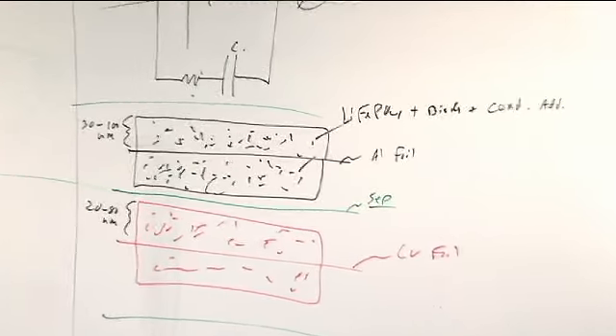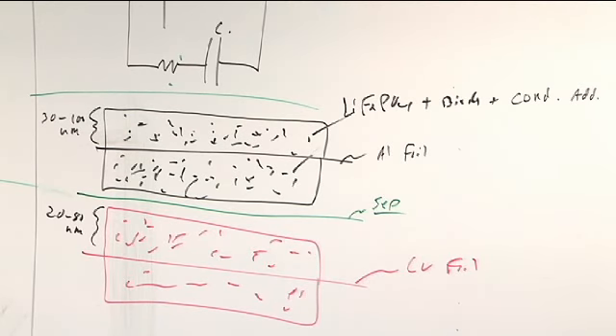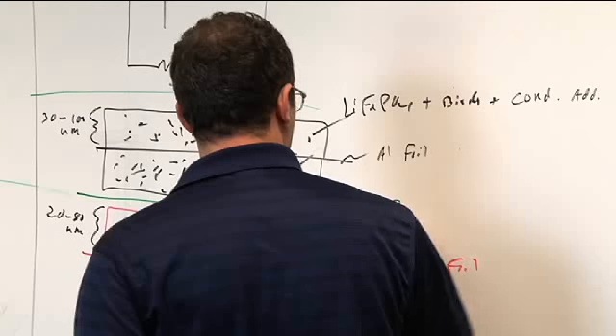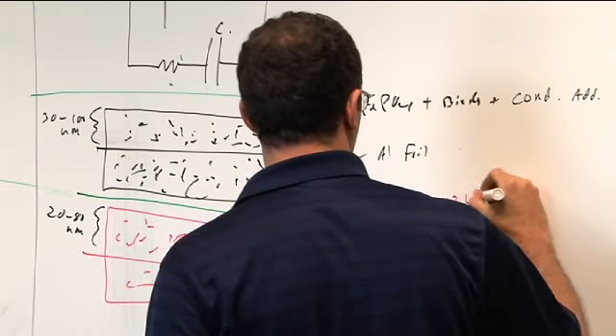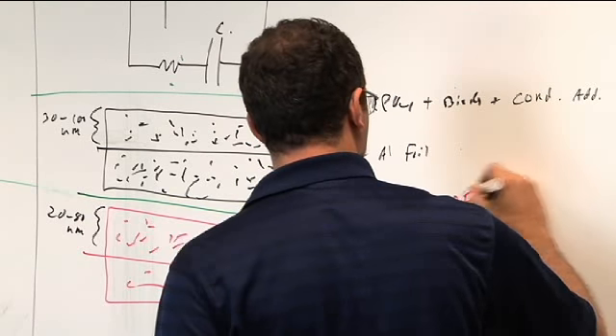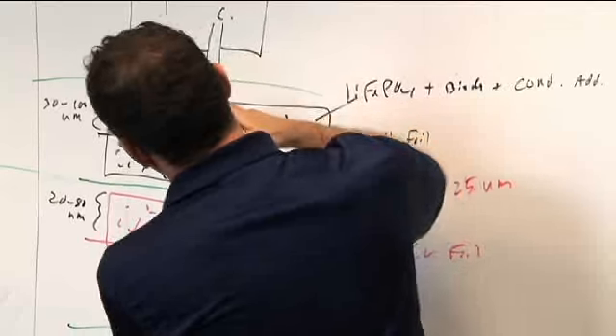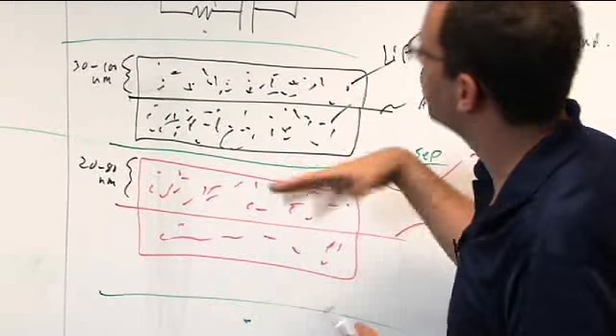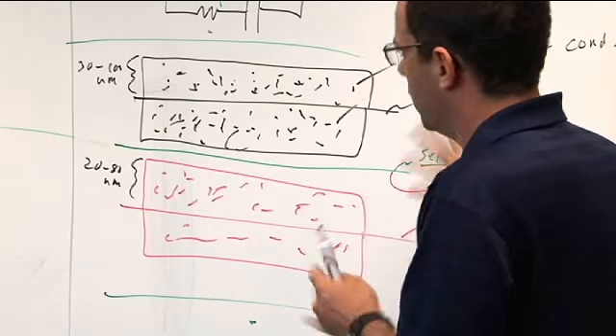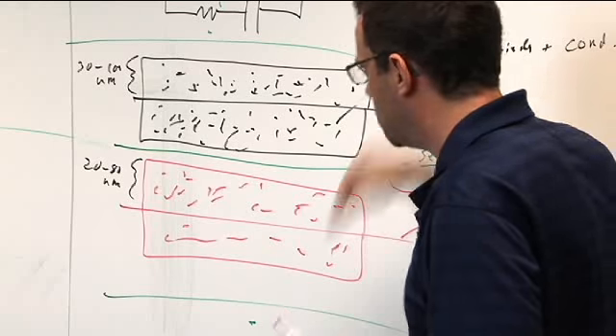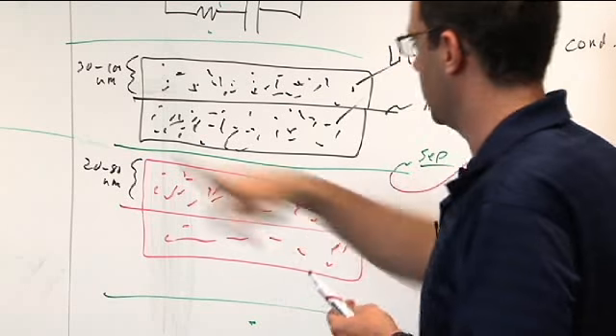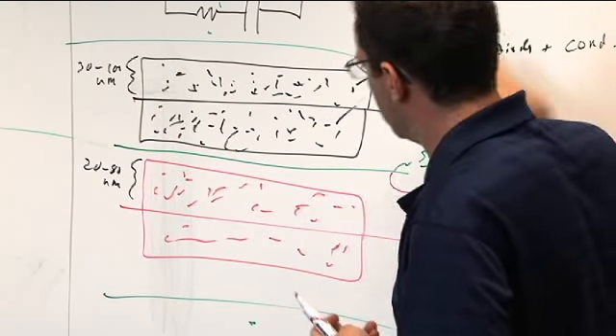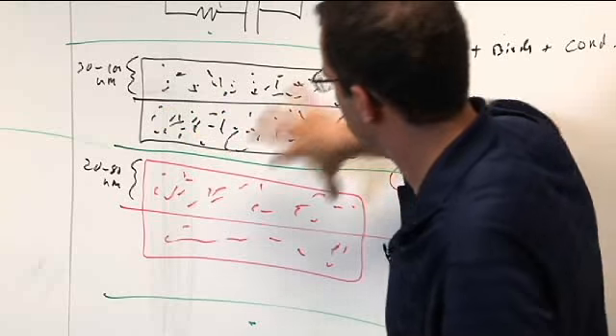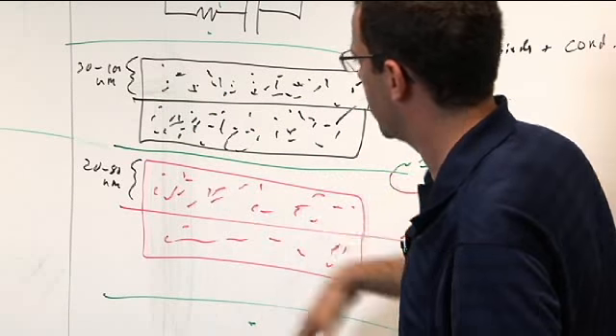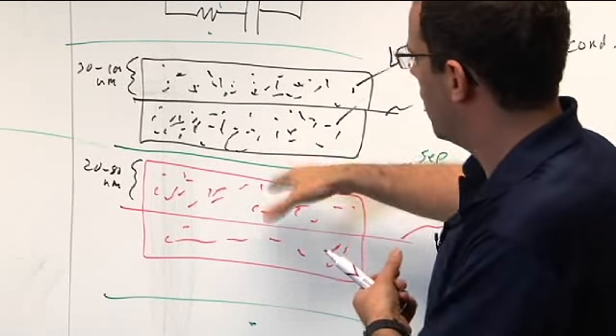What's the rough separation between the two? Oh, they are at intimate contact. Okay, so the thickness of the separator is about 25 microns. And there is no open space. This is backfilled. So we wind these up relatively dry, and then we vacuum backfill it with our electrolyte. Okay. And the electrolyte infiltrates all the pore structure in both the separator and in the electrodes, but there's no